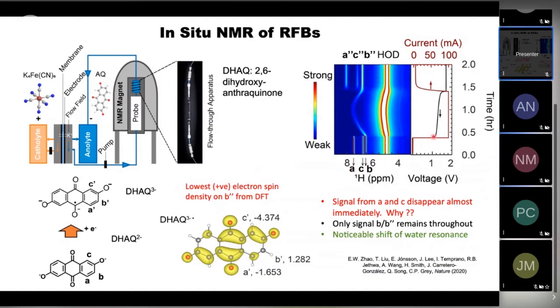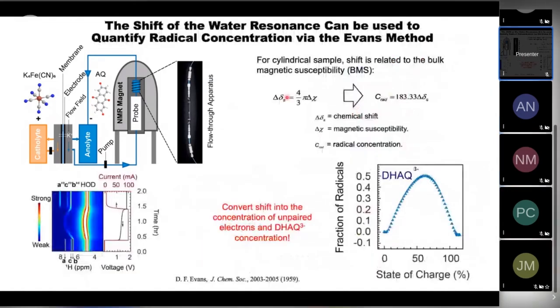And what's interesting, when you charge your battery, which results in the reduction of the quinone molecule, first to the radical and then to the 4- anion, where you put in two electrons, is that you see two resonances disappearing very quickly, and the third shifts, and then it comes back to the resonances of the diamagnetic system. And even the water resonance shifts. We can do DFT, and we can show that the proton B has the smallest hyperfine shift, which is probably why we can still see it. But there are some other questions or other interesting things.